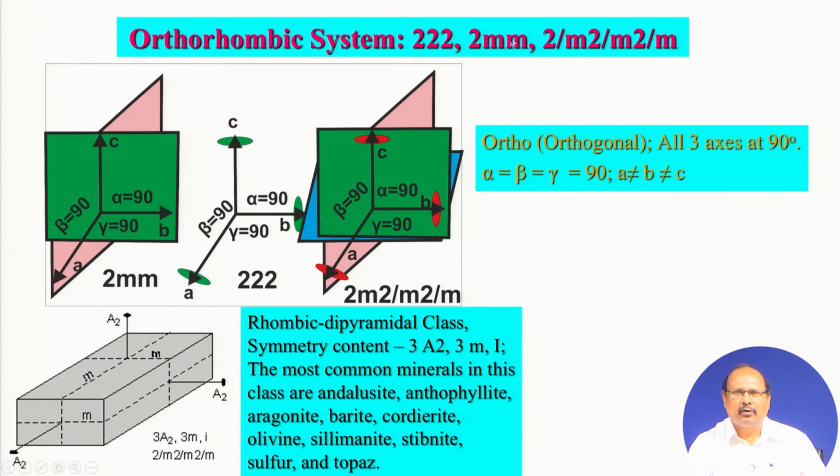And in case of the normal crystal class of the orthorhombic crystal system, in this particular case you have three two-fold axes of symmetry like this orientation, and this orientation, and perpendicular to it. So, if you have the C crystallographic axis and a two-fold axis of symmetry oriented along this, it coincides with this, and the plane is perpendicular to it.